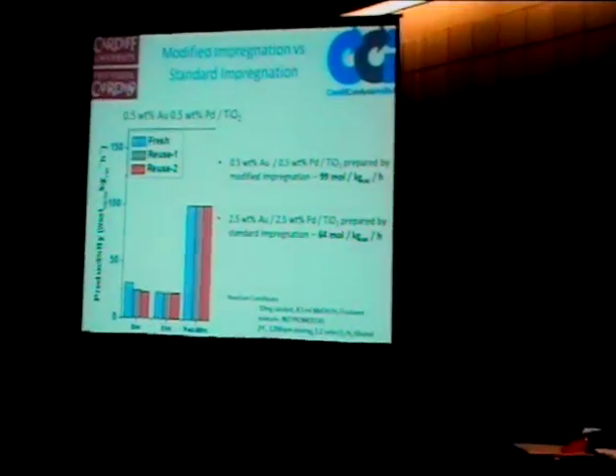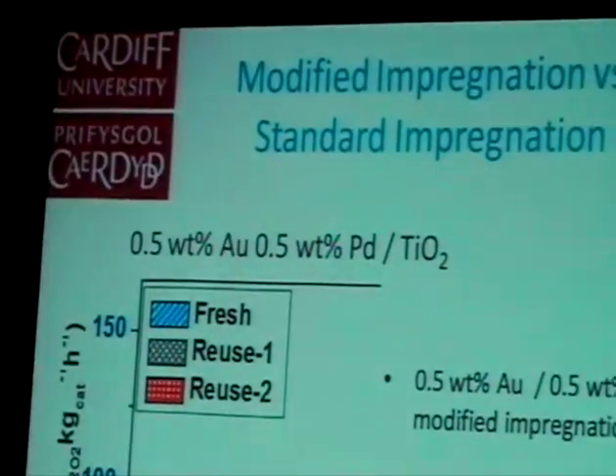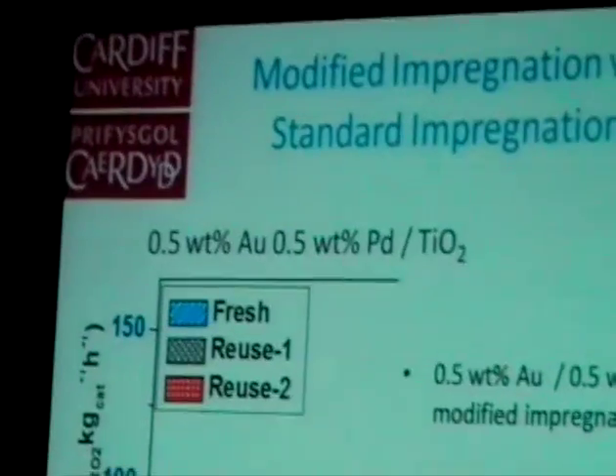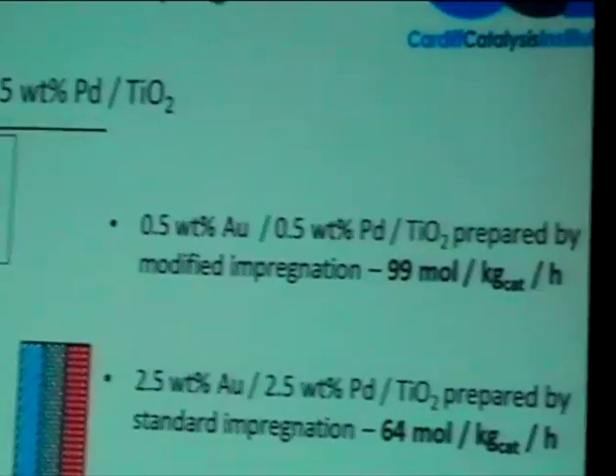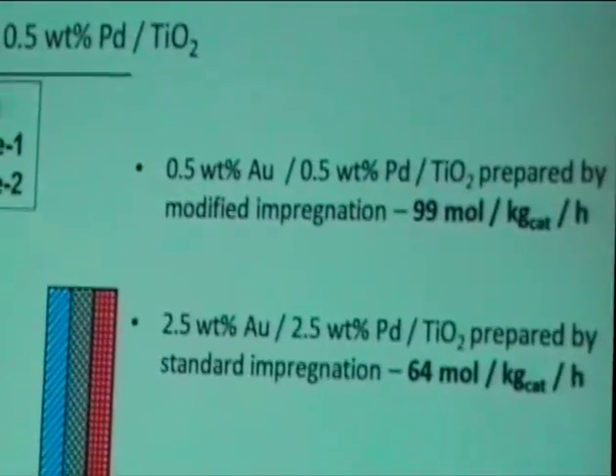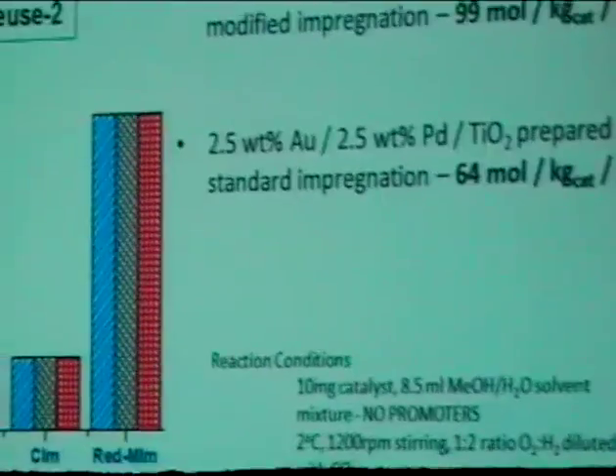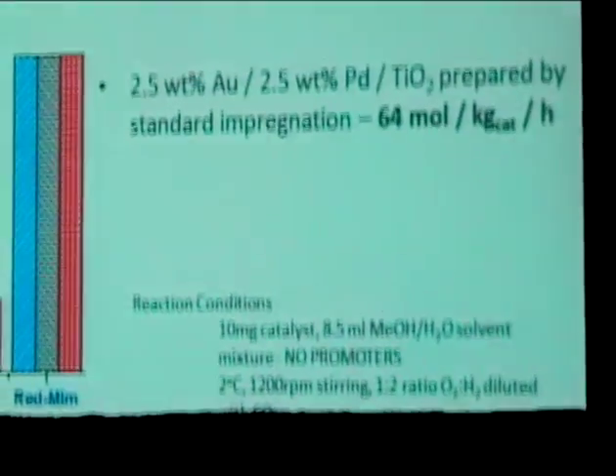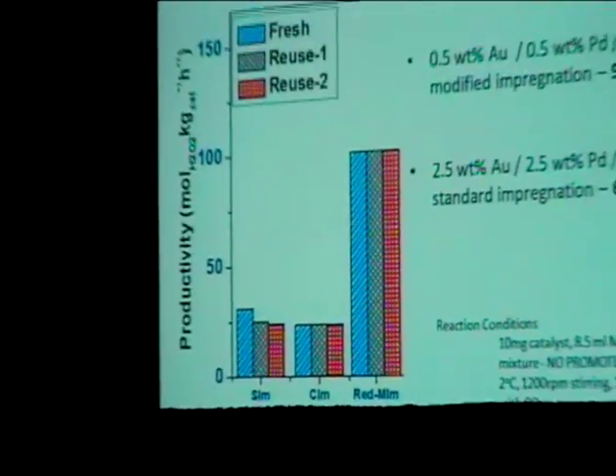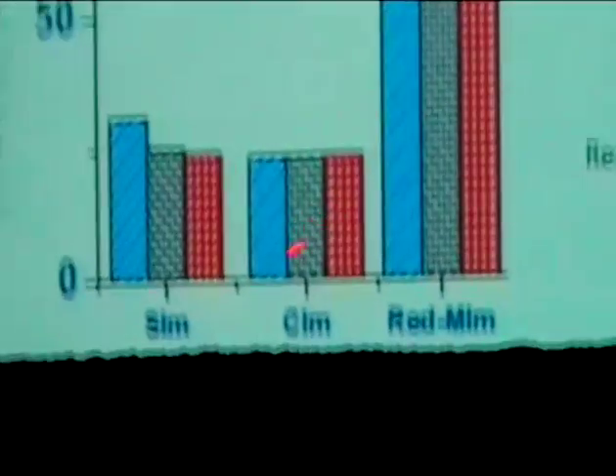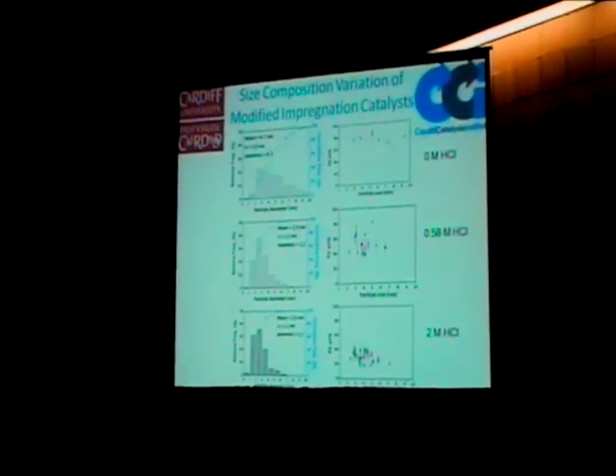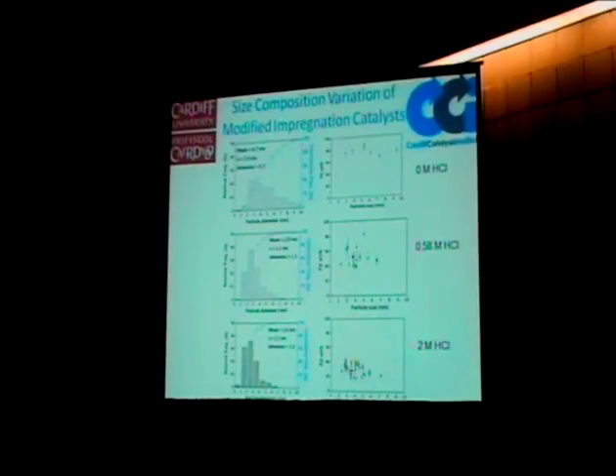So now we test these catalysts for hydrogen peroxide synthesis. This is our modified impregnation against our typical everyday standard impregnation. So we're using a 1 weight percent metal loading. From these results, this is a sol immobilized catalyst which goes through the same procedure, the reductive heat treatment. This is our conventional impregnation, and this is our modified impregnation. And I should stress we're using this catalyst here. It's a particle size of around 3 nanometers, and roughly 50-50 gold to palladium ratio in the nanoparticles.